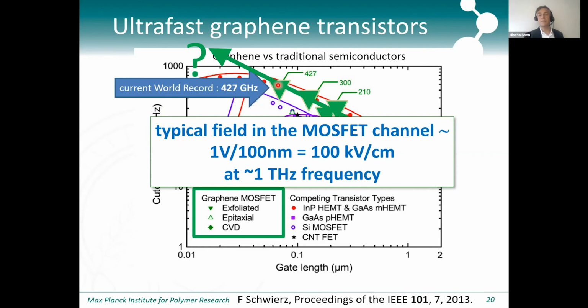Now you have to realize that for this 427 gigahertz graphene-based transistor, you have a gate length of about 100 nanometers. You have a voltage over the channel of typically a volt. It can be half a volt, it can be 2 volt, but it means you get up to field strengths of about 100 kilovolt per centimeter. And so in this case at 0.42 or 0.43 terahertz, so at roughly a terahertz frequency.